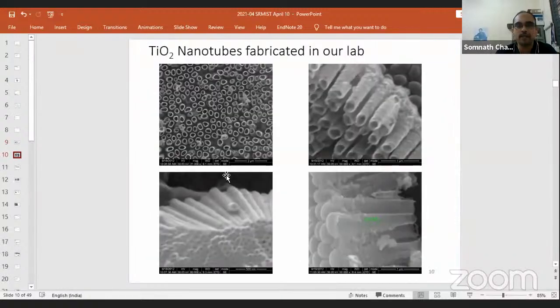As you can see here, these are the TiO2 nanotubes fabricated in our laboratory. In fact, almost every day somebody or other makes these nanotubes. Probably I will convince at least some of the 70 participants I can see now, at least 7 of 70, 10%, if that is good enough, will say, yes, sir, it is beautiful. So that is why I call it the beautiful world of 1D nanostructures. You can prepare them in different diameters and different lengths. The length can go up to 50 micron or more. As you can see in the bottom one, conical, compact, separated nanotubes of different kinds can be prepared. Of course, this is our work we are showing.